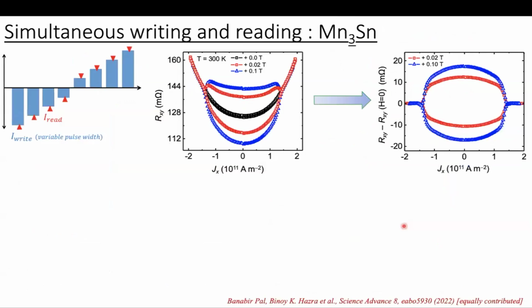So far I discussed one protocol where we apply a 100 millisecond writing pulse, and then we wait for 0.5 millisecond, and then we apply a small read current to measure the transverse resistance, and we calculate the switching percentage. Now we performed another type of experiment where writing and reading were done at the same time. We apply the writing pulse, and then apply the read and measure the transverse resistance. This is the data for different bias fields. At zero field, there is no switching, that is the black curve. And when the bias field is finite, we observe some switching. But the switching graph looks completely different compared to the earlier case, where there was a delay.